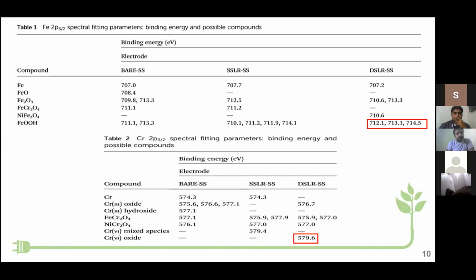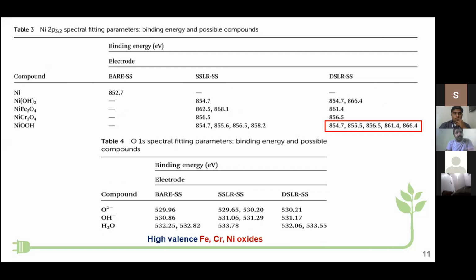Table 3 also shows that nickel 3+ is predominantly formed in the case of double side laser irradiated stainless steel, which is further supported by the O1s spectral fitting parameters. From the XPS survey spectrum as well as the tables, we confirmed that during laser irradiation, high valence chromium and nickel oxides are formed over the surface.